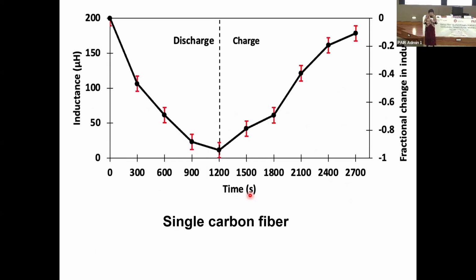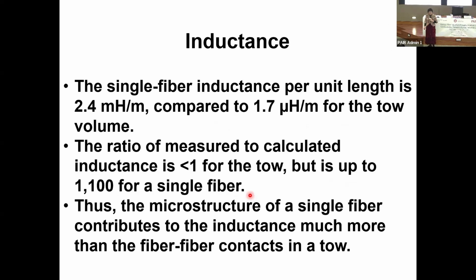And the fiber waviness, on the other hand, within the tow, helps to contribute to the inductance of the tow. The inductance, this is for single carbon fiber, can be essentially killed by short circuiting, and then restored by subsequent open circuiting. The single fiber inductance per unit length is 2.4 millihenry per meter compared to 1.7 microhenry per meter for the tow.